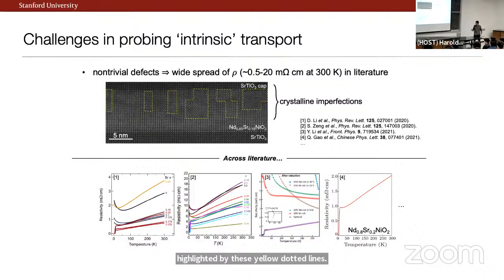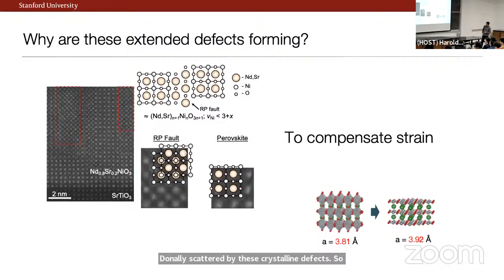We think this is relevant because if you look at our work and the first few independent groups studying this problem, a lot of the things like the superconducting transition were common and quantitatively common across these samples. But things like resistivity, the electrical properties that we were so interested in, were bouncing around by a factor of 100, sample to sample, group to group. So it's no way to make a living trying to study this, right? And so our understanding was that these sorts of extended defects were dominating scattering. So electrons running through this material were being dominantly scattered by these crystalline defects. So again, back to a materials question: can we control them?